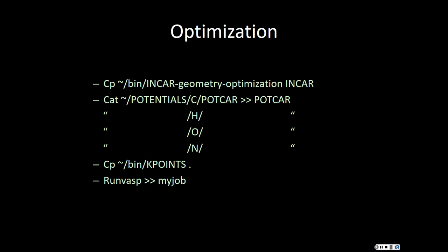You are very correct. VASP is a silly robot. It is not thinking for us, so if you make mistakes, it's our responsibility. When you look at your POSCAR file, it lists atoms of element type 1, element type 2, and the name of the element that you type, like carbon, hydrogen, means nothing. It reads the type of element based on the contents of the POTCAR file.